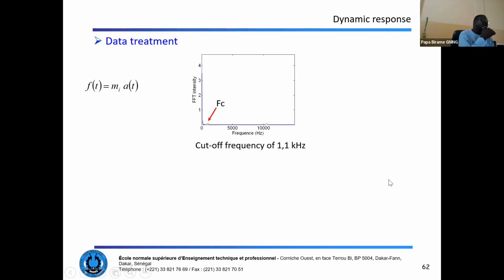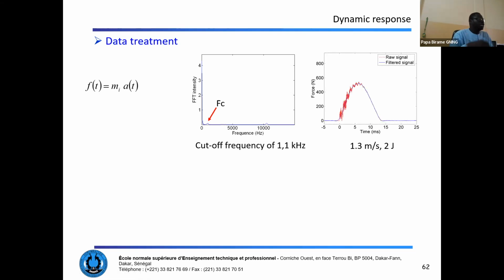So after the impact, we can eliminate the noise by Fourier transformation, and we have the evolution of the force depending on the time, and the impact duration is around 15 milliseconds.